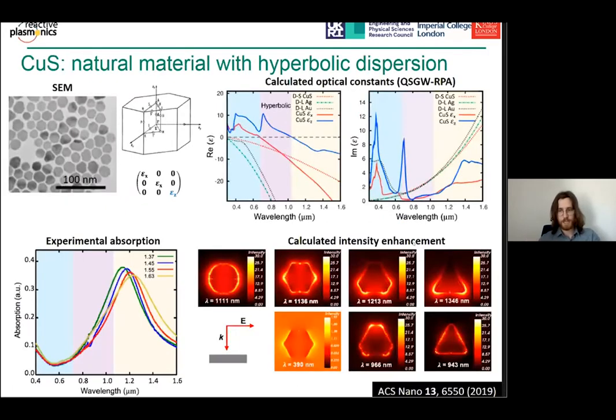So in addition to top-down fabrication processes and thin film deposition, we're interested in bottom-up fabrication processes and materials as well. So one of these materials is copper sulfide, which is a material that you can fabricate nanocrystals of. So we completed a characterization of the optical properties of these copper sulfide nanocrystals, both experimentally and theoretically, with computational modeling. And what we see is that it is a material that displays natural hyperbolic dispersion in the wavelength range of 670 to 1050 nanometers, whereas in the long wavelength range, it displays typical metallic behavior.